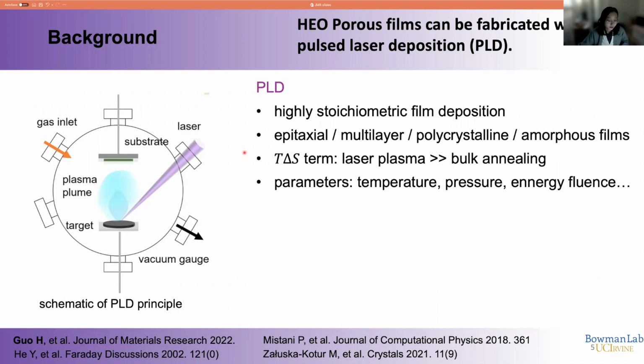For using PLD to make HEO films, PLD has a special advantage because it has a very high T delta S term. I mean, when the laser hits the surface of the target, the temperature at the surface of the target is higher than the evaporation temperature of the target materials. So the T delta S term is much higher than in bulk annealing. That means it's easy to make the HEO phase stable using PLD.